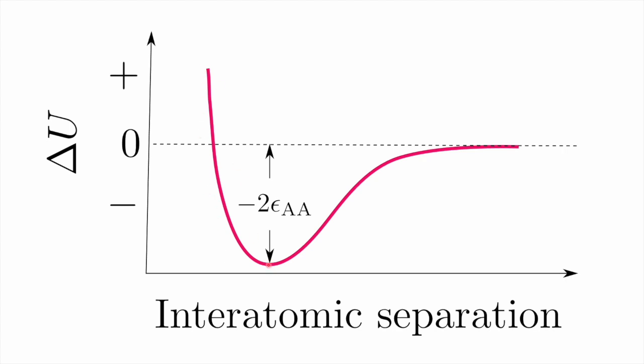So this would be the separation, the ideal separation of the two atoms, and that represents a decrease in energy. In other words, you formed a bond relative to the point where they were infinitely separated. And I've written this as minus 2 epsilon AA. This kind of curve actually has many uses. For example, it determines the modulus of the material, and so on. So you can, in fact, calculate these curves using first principles methods, but that's another story. All I wanted to note is that when I bring two A atoms next to each other, they will form a bond with a reduction in energy of minus 2 epsilon AA.